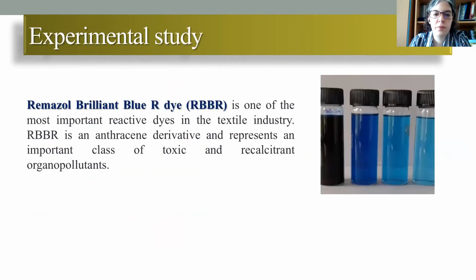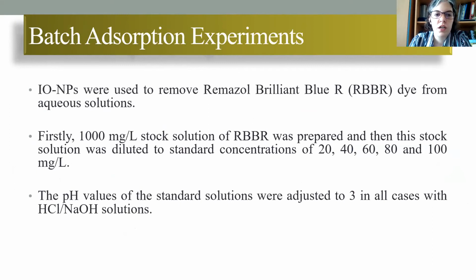For the adsorption experiments, we used Remazol Brilliant Blue R dye, which is one of the most important reactive dyes in the textile industry. It's an anthracene derivative and represents an important class of toxic and recalcitrant organopollutants. Iron oxide nanoparticles were used to remove the dye from aqueous solution. Firstly, a 1000 mg per liter stock solution of dye was prepared and diluted to standard concentrations of 20 to 100 mg per liter. The pH values of the standard solutions were adjusted to 3 in all cases using hydrochloric acid or sodium hydroxide solutions.